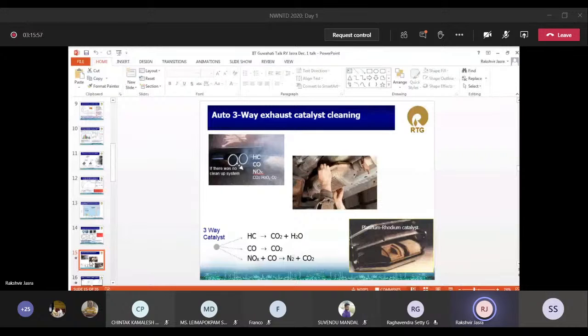Because it converts hydrocarbon to carbon dioxide and water by oxidation, and carbon monoxide, which is produced during the burning of fuel. Hydrocarbon is also produced, which is not burned fully. Then carbon monoxide gets converted to carbon dioxide. It should not be emitted to the atmosphere because it's a poisonous gas. And NOx also gets converted to nitrogen and CO2 by reaction with carbon monoxide. So this catalyst has to do all these three reactions. Then only it is really an effective catalyst.